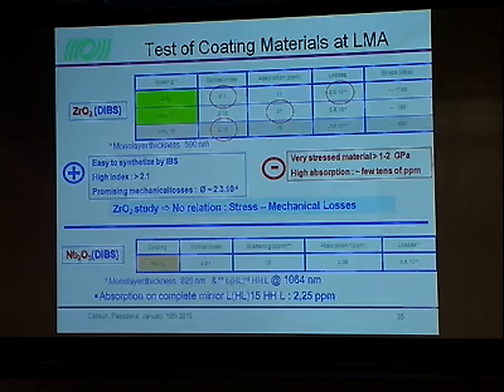The first material is quite often used in optics. It has actually pretty low mechanical losses compared to tantalum pentoxide, but the absorption is too high, so it cannot be used basically because of absorption. And also the stress inside the coating is pretty high. We are at the level of a couple of gigapascal, which is a relatively high number.